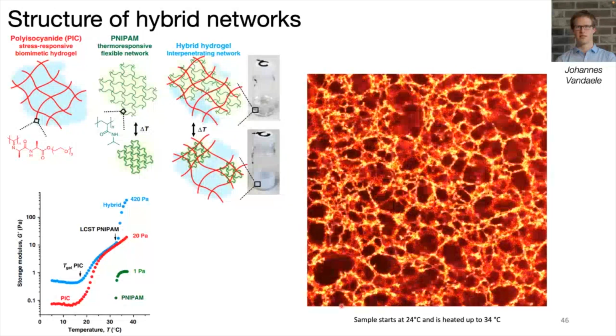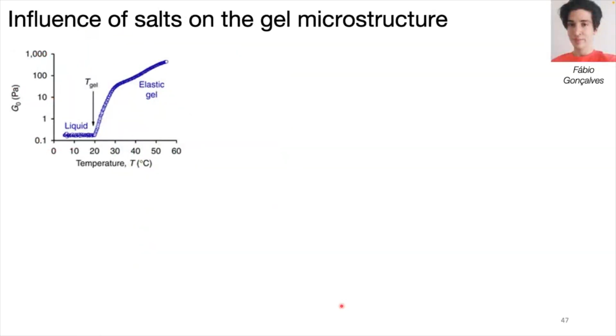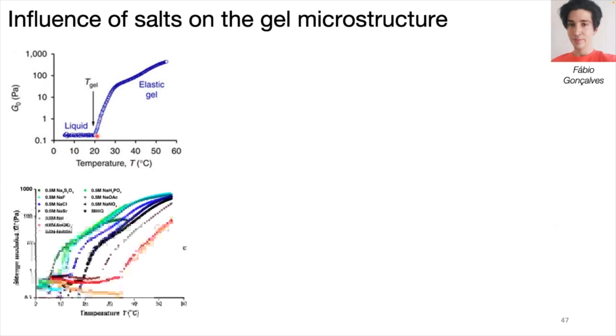And then another thing that I still want to show you is to play a little bit with the solution. So if you have PIC only, the gelation temperature is around 18 degrees. But if you add some salt to the solution, you can nicely change this gelation temperature. You can go to lower values or to higher values.